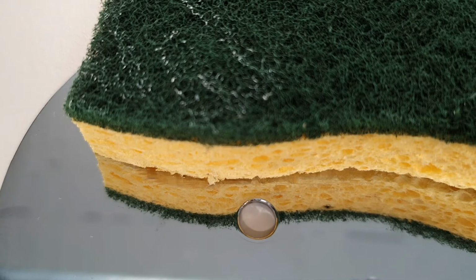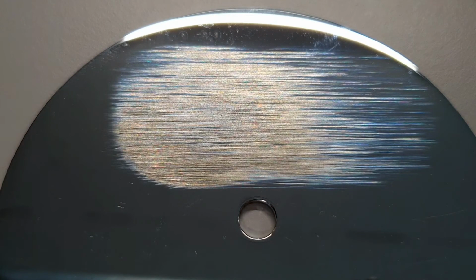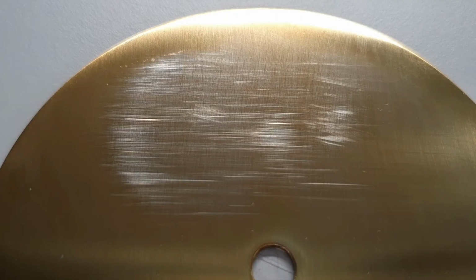The second test series we have performed with the Scotch-Brite heavy duty scrub. Obviously this scrub should not be used for kitchen and bathrooms. If you look at the sample, this is the electroplated chrome sample. Most of the coating has been rubbed away after the 1000 cycles. This is the gold-plated PVD coating on brushed surface. Surprisingly, also that very hard PVD coating has been scratched and removed away in certain areas.